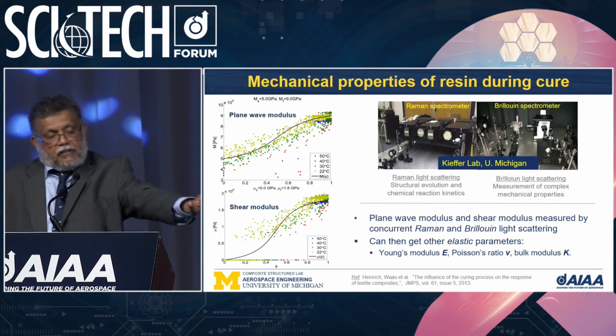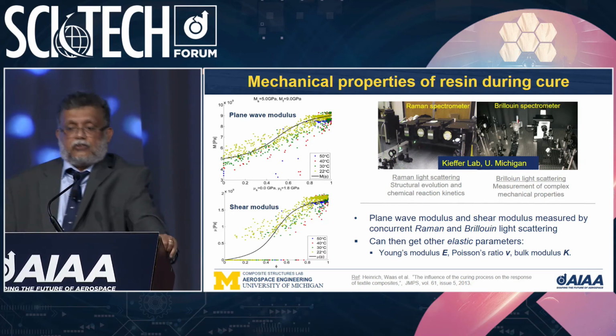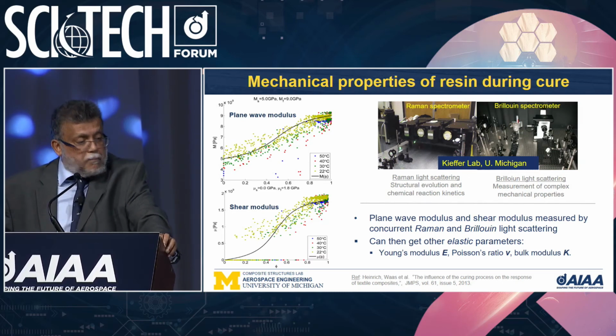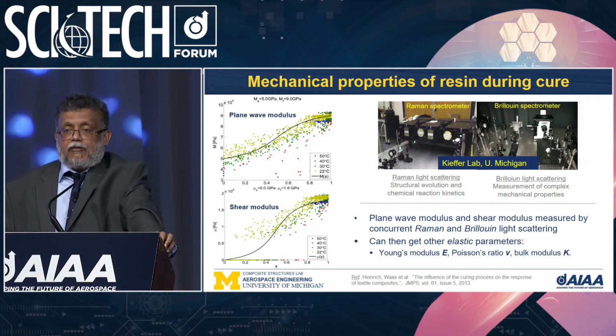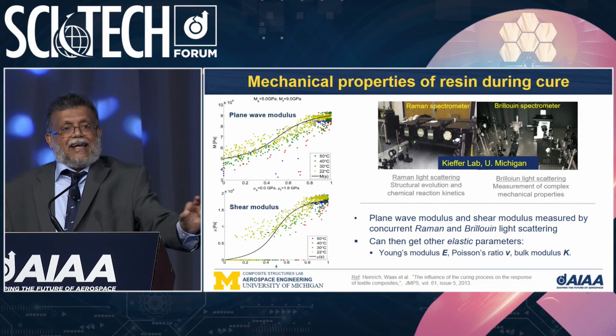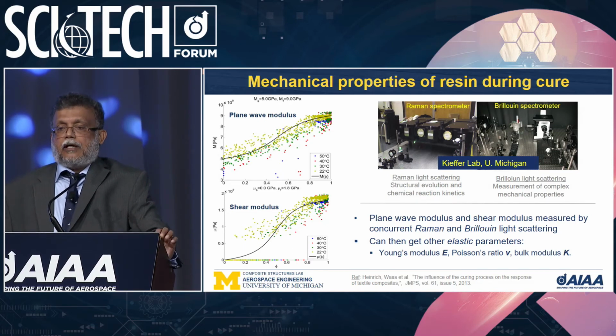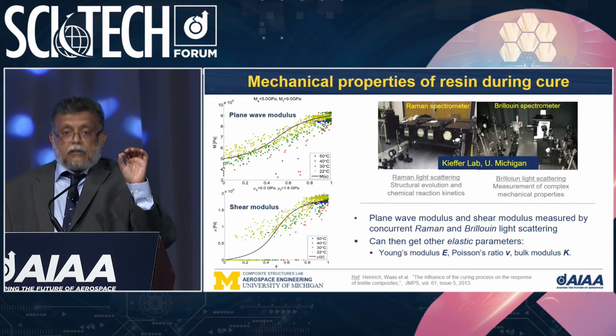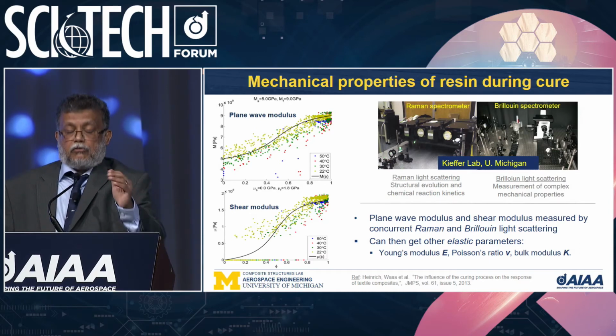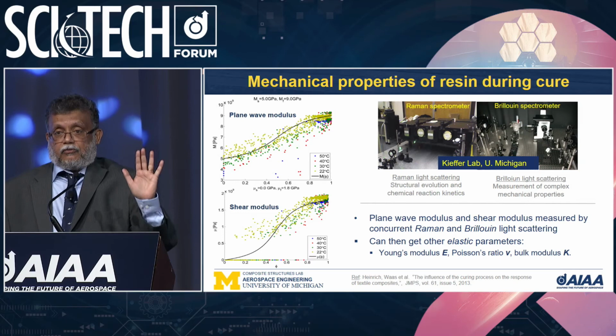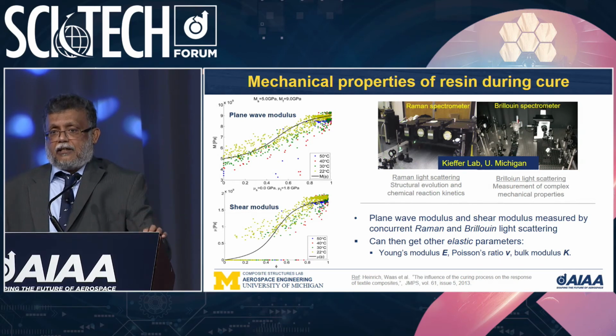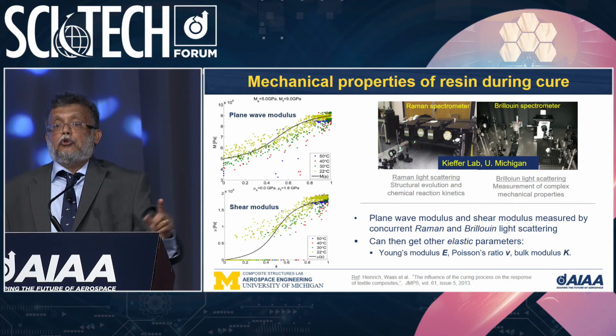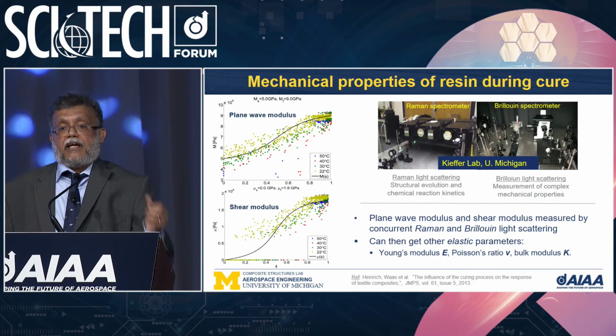But before that, we have a collaboration with our material science colleague John Kiefer, where we measured using Brillouin and Raman scattering how the plane wave modulus and the shear modulus evolve during the curing process, so that from that we can extract the Young's modulus and the Poisson's ratio of the resin during the cure cycle. Now, I want to emphasize that different cure cycles lead to different evolution of curing or solidification of the resin.